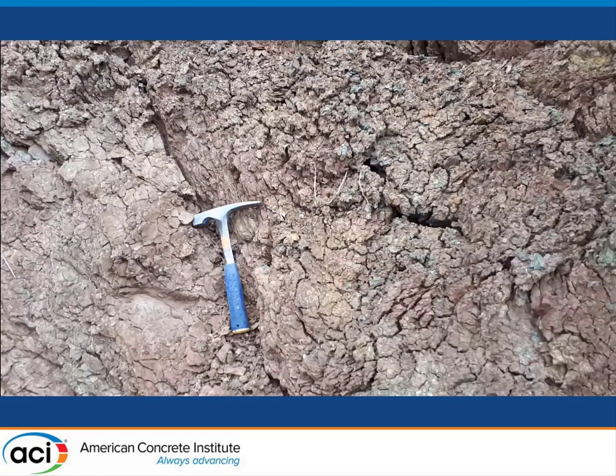And then this is the other main ingredient, Danish clay. This is the Danish plastic clay, as we call it, which is a quite widespread clay formation. It is extremely pure. It contains around 90% clay minerals for most of the parts. The clay mineral composition is typically smectitic.